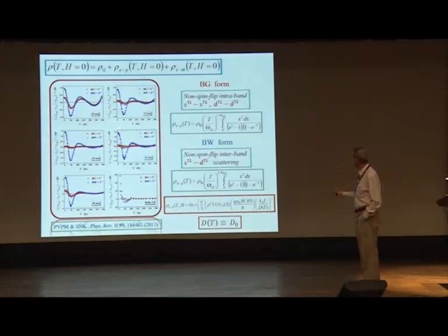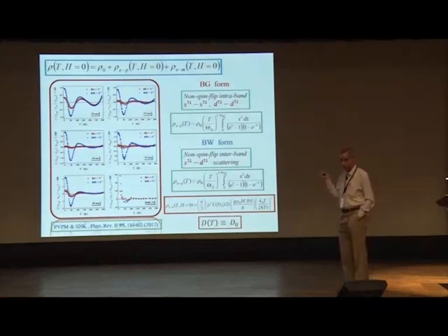And now in some cases you do see that it is not systematic. That means by introducing the electron-magnon term of T square form, we are able to reduce these deviations and describe the data better and better. Okay? Now, the next step is obviously to include the thermal renormalization of spin wave stiffness, which we have neglected in this case, and then see what happens to the deviations.